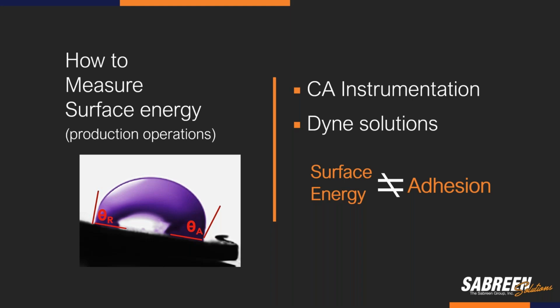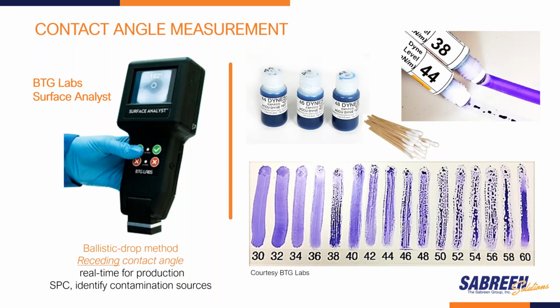So we're going to look at different ways of testing the surface using contact angle instrumentation as well as dyne solutions. I know all of you are familiar with the dyne solutions. I'm not a fan of them, and you're probably not either. We all know there's a great deal of variability that happens as we try to test this. We can use the dyne pens, and they're generally a directional indicator of what the surface energy is, as are the solutions. But they're highly unreliable, and just by the fact that the tips of the pens come in contact with the materials, it contaminates the tip, and that's going to happen regardless of what the manufacturer or supplier says.